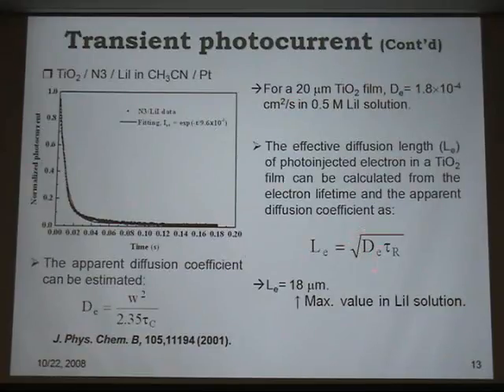Now, once you know the diffusivity, you know the lifetime of electron inside the film, you can calculate the theoretical maximum length you need for titanium dioxide, which is about 18 micrometer, and that satisfies ourselves that we only need about 3 coatings for titanium dioxide.